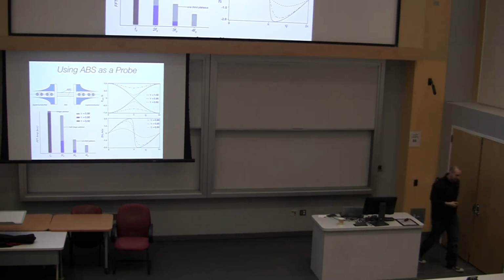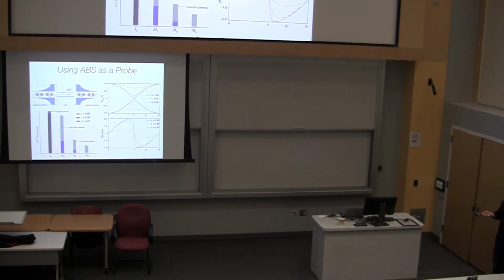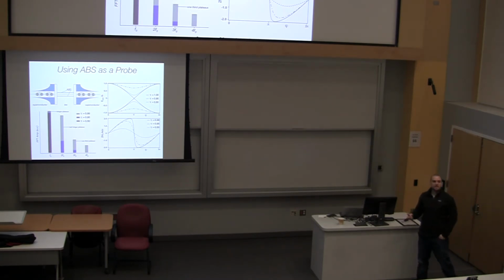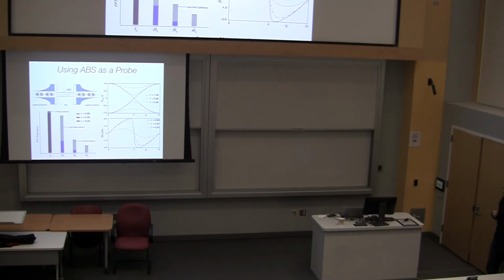And how this skewness manifests itself is, as you move from a sinusoidal wave to a triangular wave, if you do the Fourier expansion, you get higher and higher harmonics that you need to generate to form that waveform. So if I look at the Fourier transform of these, you'll see that as I increase my transmission probability, the Fourier amplitudes of the higher harmonics increase. And when I do a Shapiro step measurement, if I only had the fundamental, I would see only steps at the integer values that you would expect. But when you start to add in these higher harmonics, you start to see steps at half of what you expect, a third, and a quarter. So if I measure the AC Josephson effect and see these subharmonic structures associated with a skewed current phase relationship, I can say something about what the Andreev bound state spectrum of my device actually is.